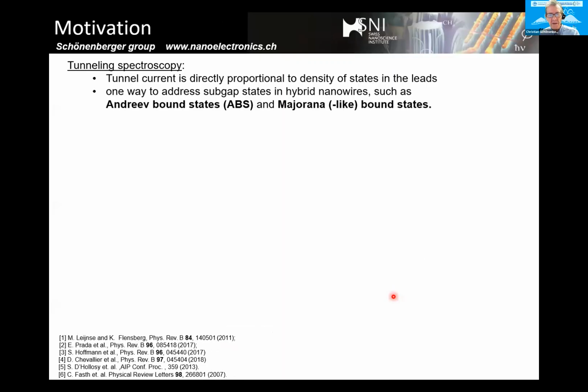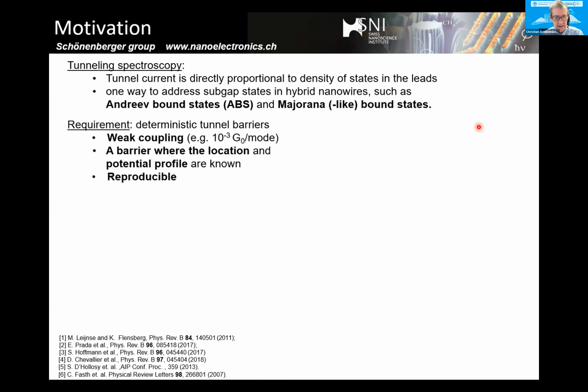So tunneling spectroscopy is probably the standard thing which is done today when one is searching for Majorana-like bound states. And most often these tunnel barriers are generated in nanowires using side gates. But what we really want, as emphasized before this morning already, is tunnel barriers which couple weakly so that you can really get large suppression also in the superconducting state. The location of the barrier should be very well known, and it should be reproducible.